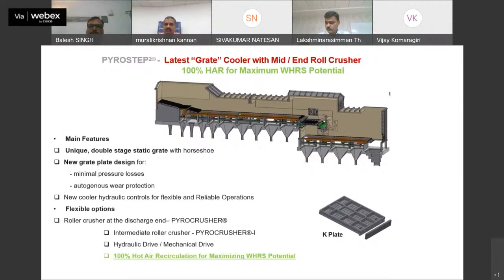When this clinker is leaving the cooler, definitely it is taking some heat out with it. To take all the heat out of the cooler, it is better to crush the clinker at the mid place and take all the heat into the mid air. So this is very much successful, and almost 0.5 megawatt enhancement is found in the waste heat recovery system.